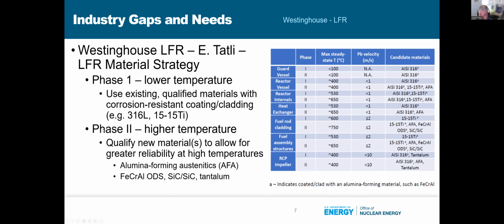But in phase 2, would they go to higher temperature, then they would want to qualify new materials for greater reliability at the higher temperatures. So maybe it's austenitic forming or alumina forming austenitics or FeCrAl or ODS with a cladding. So a more radiation tolerant cladding, but with a coating on it to prevent corrosion, or even going up to a SiC/SiC in the end.